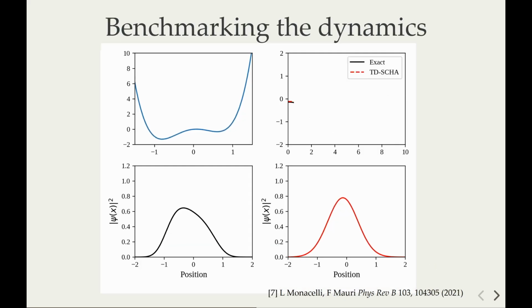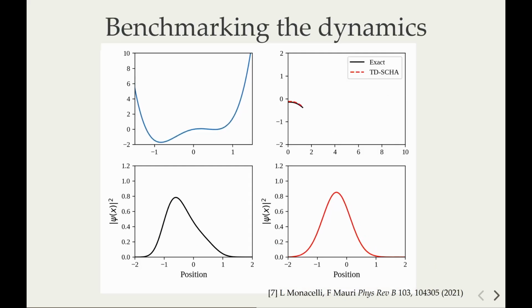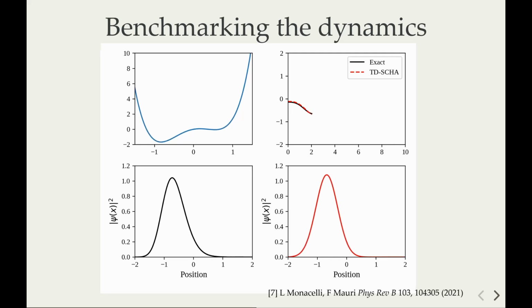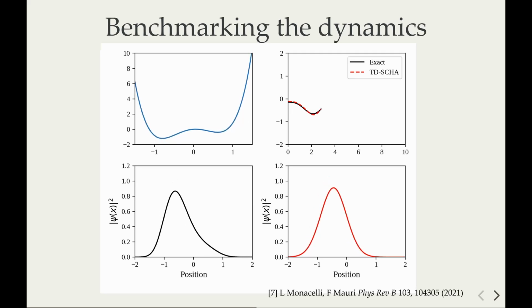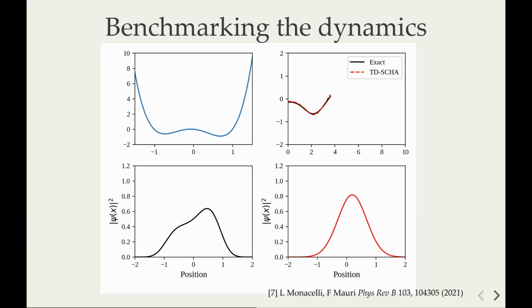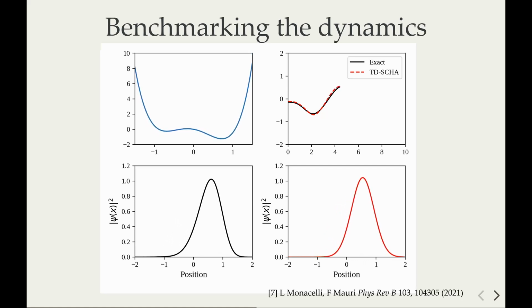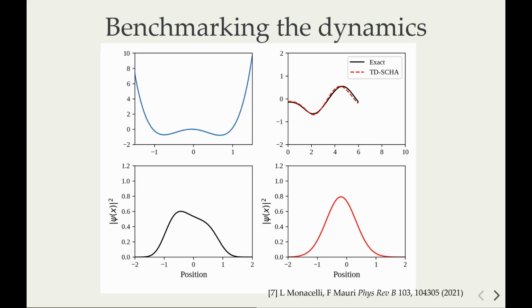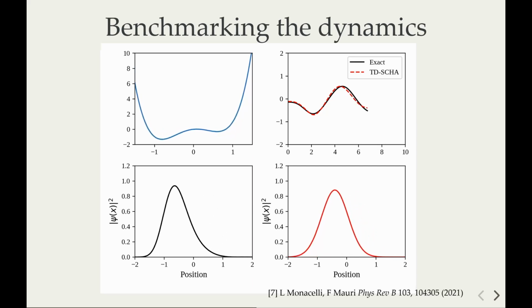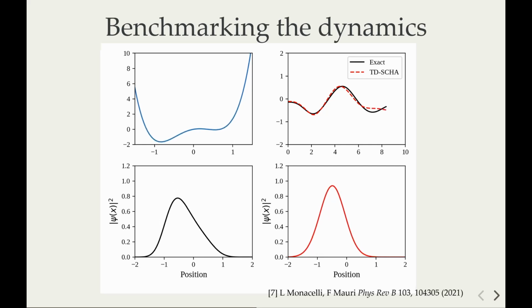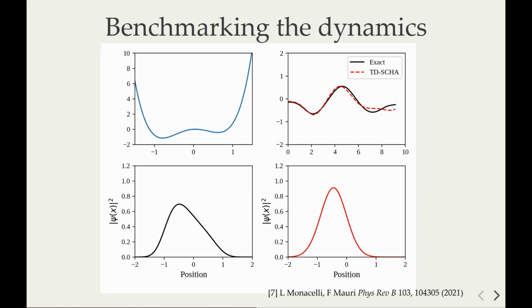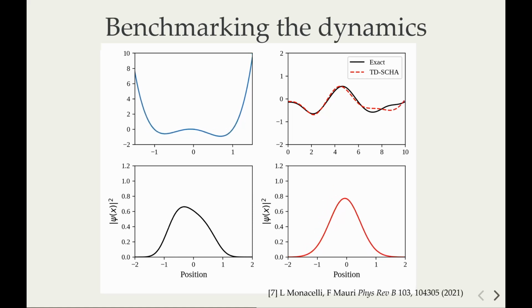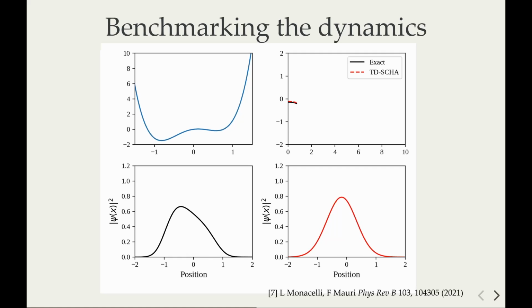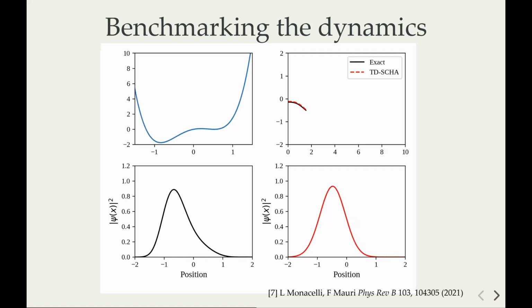Here's an example. I took the same double well potential as in the first example, and now I'm applying a time-dependent electric field which swaps the two minima. You can see in black the exact time evolution of this system, and in red what you get with the time-dependent self-consistent harmonic approximation. Indeed, the wave function remains Gaussian because that's a constraint. But if you look at observables, like the average position of ions, you see they describe very well what happens in the real case.